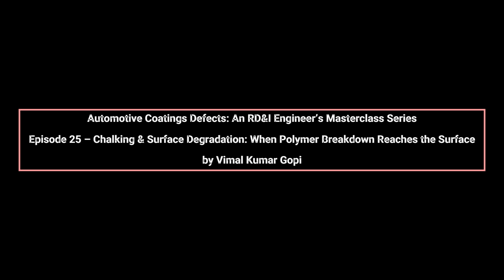From an OEM durability standpoint, chalking occurs when ultraviolet radiation, oxygen, heat, and moisture progressively break down the polymer backbone of the clear coat or top coat. As chemical bonds are broken, the polymer chains lose molecular weight and cohesion. The degraded fragments migrate to the surface, forming a fine, powdery residue that can be wiped off by hand. This residue is not contamination. It is the coating itself.